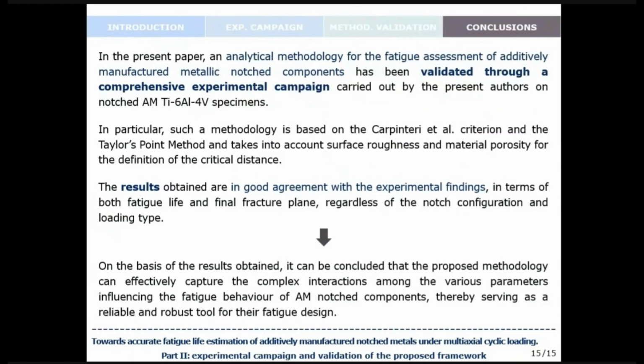In the present paper, an analytical methodology for the fatigue assessment of additively manufactured metallic notched components has been validated through a comprehensive experimental campaign carried out by the present authors on notched additively manufactured titanium, aluminum, vanadium specimens. In particular, such a methodology is based on the joint application of the Carpinteri criterion and Taylor's point method, and takes into account the surface roughness and the material porosity for the definition of the critical distance. The results obtained are in good agreement with experimental findings in terms of both fatigue life and final fracture plane, regardless of the notch configuration and the loading type.